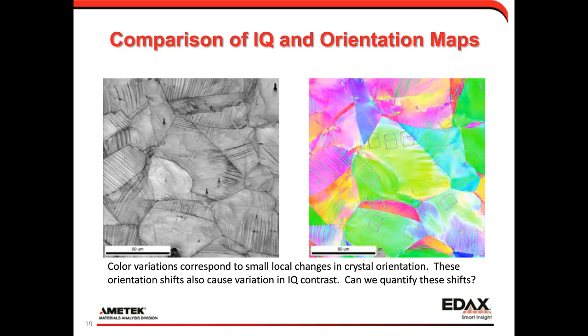And what we can see here is we can compare the image quality map to the color map, and I can go into where we see changes in that image quality. We can see in that center grain that image quality variation. If I click across there, I can see how the orientation is changing across that grain, causing both the image quality and the orientation contrast. So the question to ask here is, can we quantify these shifts?